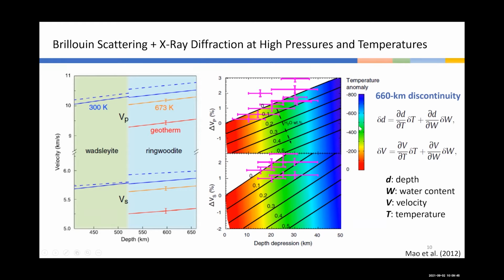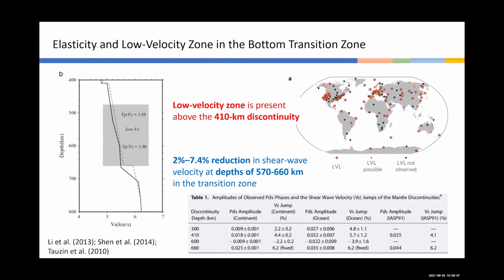So the second example that I want to give you is our most recent work that we published in GRL this year. In this work, we focused on the velocity anomaly at the bottom of the transition zone, that is 570 to 660 kilometer depths. People have observed a 2 to 7% reduction in the shear wave velocity.